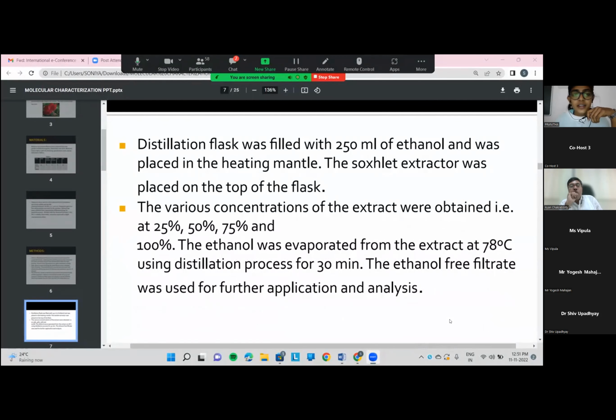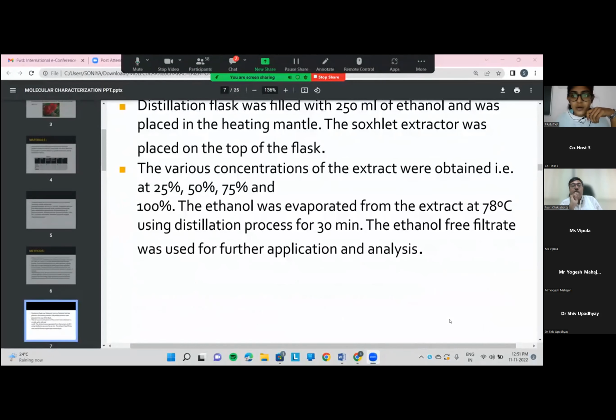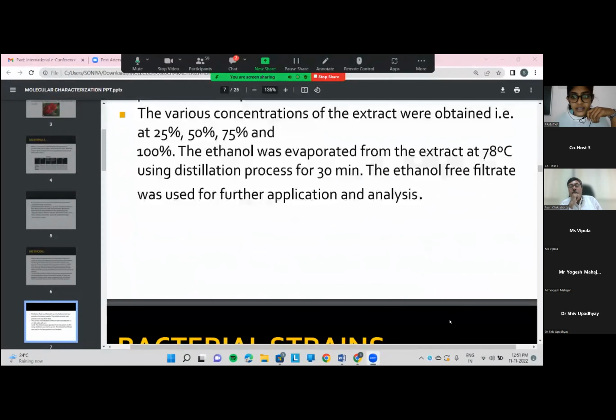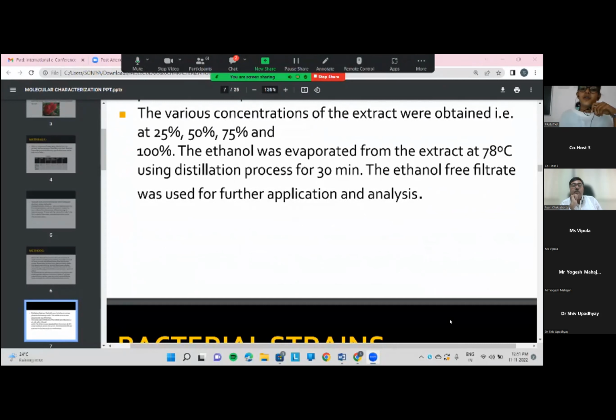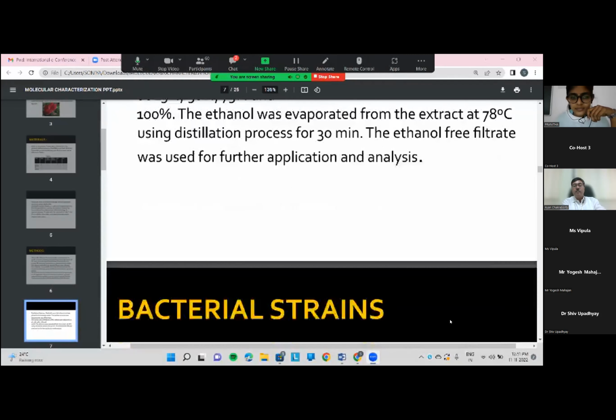the flask. The various concentrations of the extract were obtained, that is at 25%, 50%, 75%, and 100%. The ethanol was evaporated from the extract at 78 degrees Celsius using a distillation process for 30 minutes. The ethanol-free filtrate was used for further application and analysis.